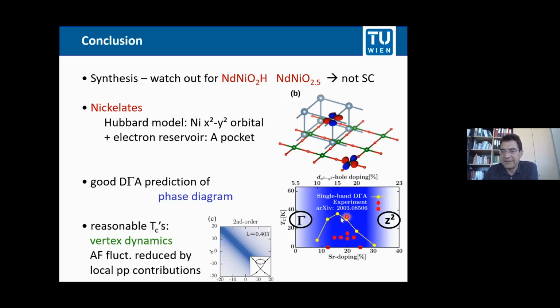And the reason why the Tc is reasonably low in such a D-gamma-A calculation is that particle-particle contributions reduce already your local vertex, and with this your antiferromagnetic spin fluctuations and your glue for superconductivity. There is still a lot to be done. There are tons of experiments coming, or the RIXS experiments now out, and I'm very sure that these nickelates will be one of the hot topics of condensed matter physics in the years to come. Thank you very much.